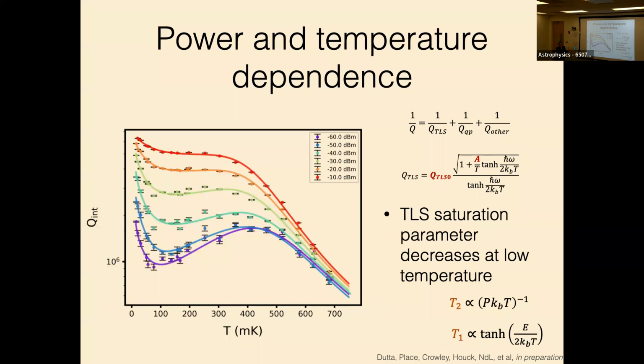Let's just take that model seriously and take a full power and temperature dependence simultaneously, and then fit the entire data set. So this is now just power dependence curves at all of these different temperatures, and we scan over a very large temperature range.